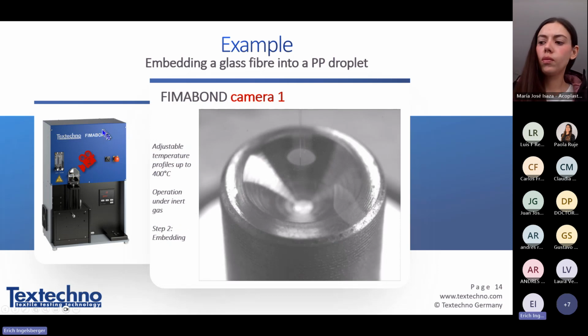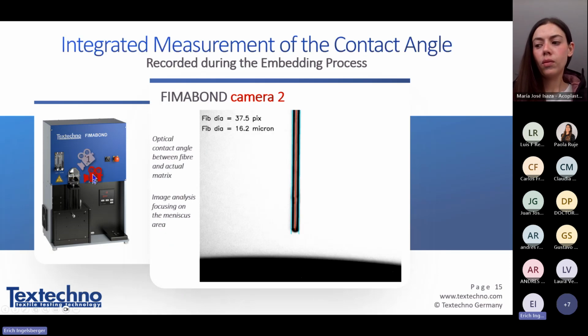When I say that the Fimabond only prepares the specimen, this is not completely correct, because it can also do some measurement, which I would like to show you right now. There is a second camera looking exactly from the side, perpendicular to the fiber, and it can measure the fiber diameter. So we have a second option to measure the fiber diameter.